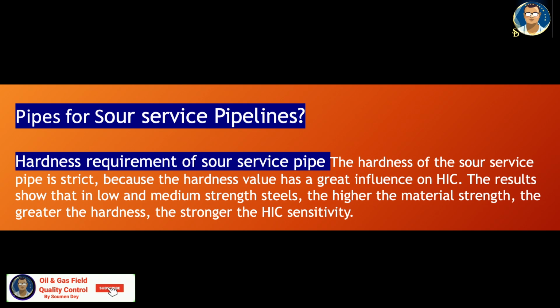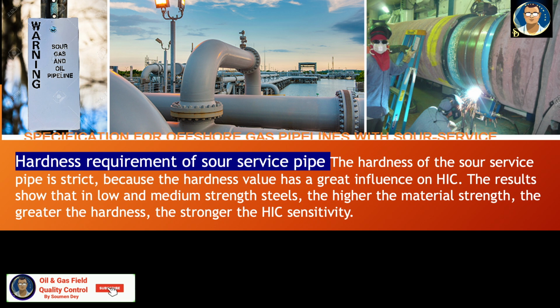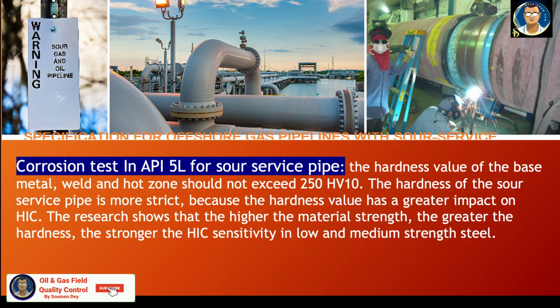Hardness requirement of sour service pipe. The hardness of the sour service pipe is strict because the hardness value has a great influence on HIC. The results show that in low and medium strength steel, the higher the material strength, the greater the hardness, the stronger the HIC sensitivity. Corrosion test in API 5L for sour service pipe: the hardness value of the base metal, weld and heat affected zone should not exceed 250 HV10. The research shows that the higher the material strength, the greater the hardness, the stronger the HIC sensitivity in low and medium strength steel.